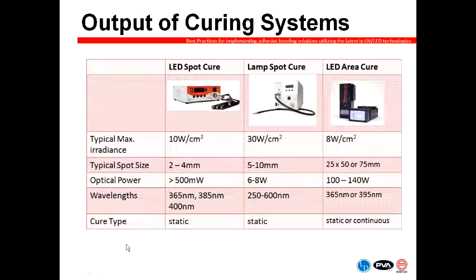One of the ways we've looked at overcoming this with LEDs is by developing what we call LED area cure systems. And so these, again, you're able to get a nice irradiance level of 8 watts per square centimeter, which will be sufficient for most curing. But with the area curing, you're now covering a much larger area, about 25 by 50 millimeters, so 1 inch by 2 inch or 1 inch by 3 inch areas. So you're now talking hundreds of LEDs within that area. And now your optical power is much, much higher. And that starts to give you much more flexibility in your curing. You're no longer limited to small spot sizes.